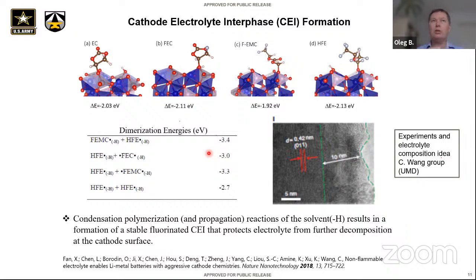And then what you create on the surface, instead of just having EC, which you deprotonate, you after that open it up, evolve CO2. CO2 goes on the other side to the SEI, forms carbonates, impedance there grows. You do not effectively passivate all the cathode, and when you passivate with this type of hydrogenation of the cathode, if fluorine goes to the transition metal, having an OH group makes it easier for cathodes to decompose, right? So you're decomposing cathodes, you're decomposing electrolytes, that's not good.